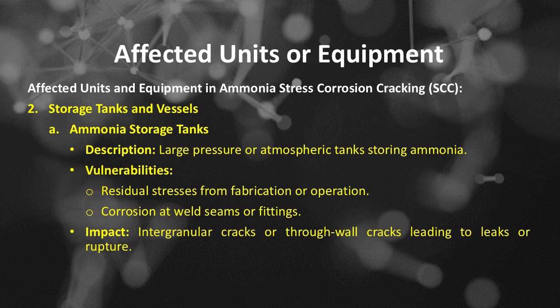Large pressure or atmospheric tanks storing ammonia. The vulnerabilities of these ammonia storage tanks include residual stresses from fabrication or operation, and corrosion at weld seams or fittings. The impact on these ammonia storage tanks would be intergranular cracks or through-wall cracks leading to leaks or rupture.